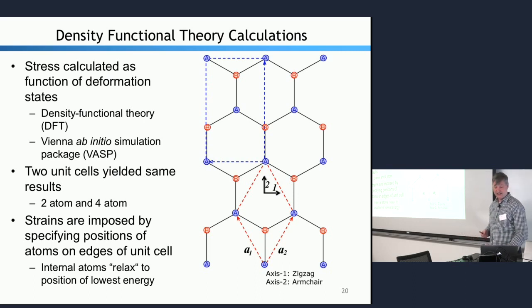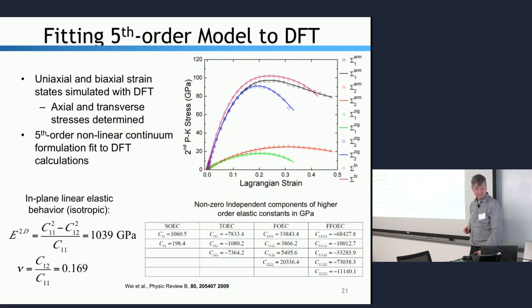Right? So the nice thing here is that now we can just take isotropic graphene, do a single unit cell or a couple unit cells just to check, and we just strain the material and look at the energetics and take some derivatives and do stress strain in that way. All right, so that's the idea. So each one of these dots here is a DFT experiment. And now what we do is we adjust these 14 elastic constants so we can fit all of these experiments well up to very high displacements.